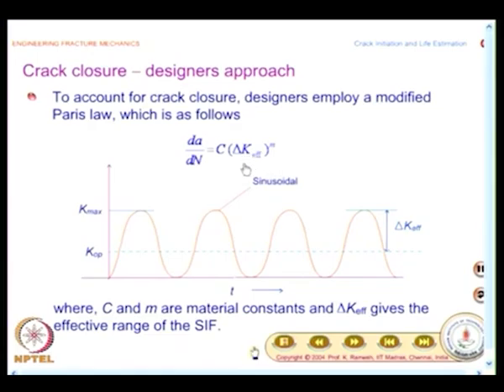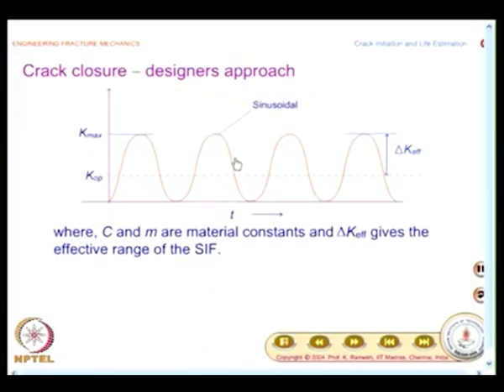Now, the question is how to find delta K effective. That is where the challenge lies. It is not a simple task. Conceptually, the crack is effective only part of the cycle. So, you look at what is the effective delta K rather than the actual delta K. So, you have to find out how to get delta K effective. Several models have been proposed. People have done experimentation and calculated it, and you will also have to bring in the effect of stress ratio R. As a function of R, how does delta K effective change? So, this is how research proceeded, and we will see how they developed delta K effective.